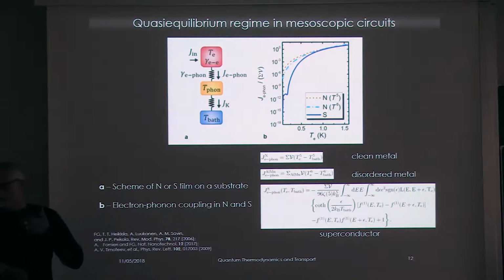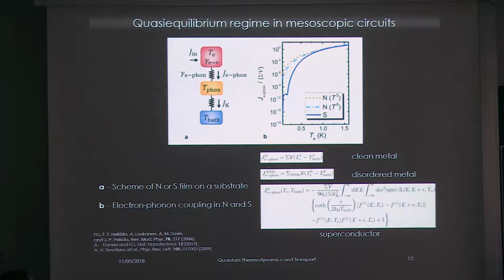The difficult thing in dealing with thermal current, thermal transport, is that while in electric transport the charge is conserved in a conductor, here the heat current is not conserved in toto, in general. So we have losses everywhere, in the universe. So the ability to deal with thermal transport is to understand where the losses are and how to quantify the losses existing in the system. This is the point. The main loss in metals and superconducting systems, in solid state structures, is due to electron-phonon coupling, the interaction between the electrons and the phonons of the lattice.